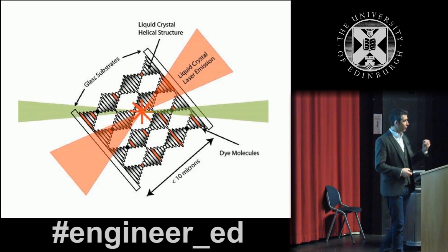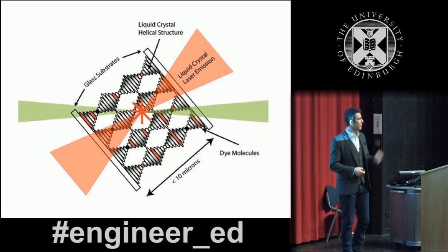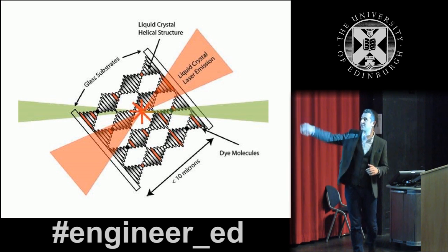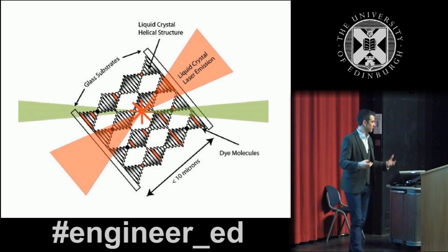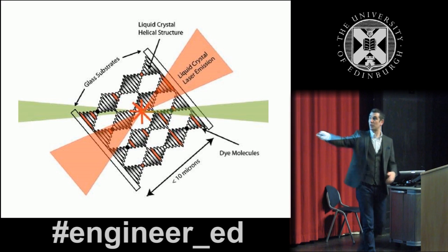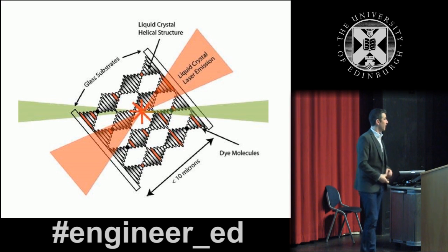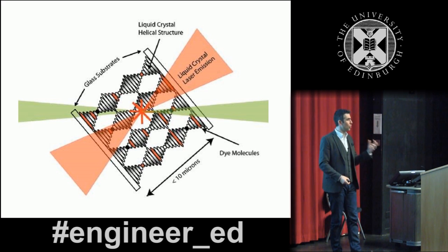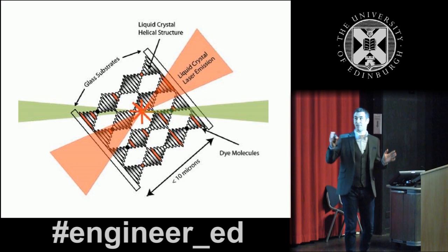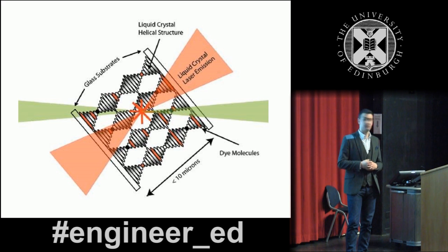And we choose our fluorescent dye molecule that emits light again at the laser wavelength we want, and then we resonate that fluorescence within the resonant cavity using our chiral structure. And that means all we've got left to do is to excite the system somehow. We shine a fixed wavelength laser onto it, something that is absorbed strongly by those fluorescent dye molecules. Those dye molecules then fluoresce, and that fluorescence is resonated in the cavity, which gives a stimulated emission.